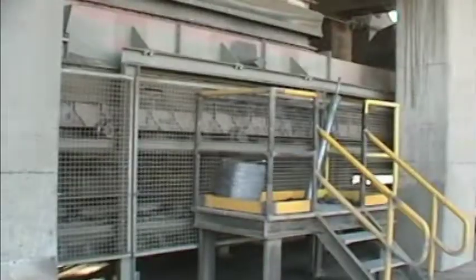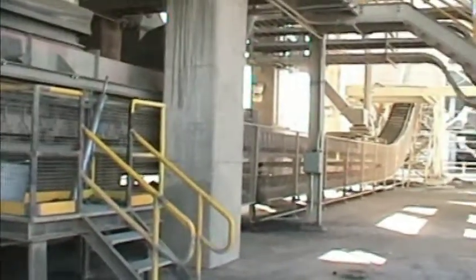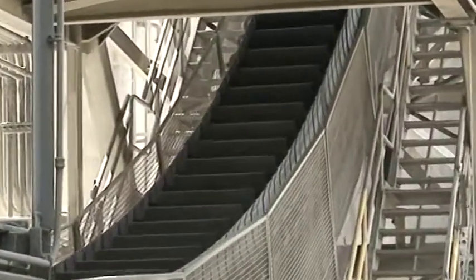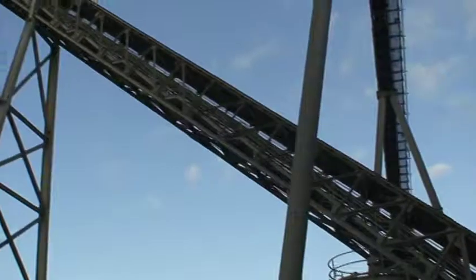Once in the cooler, 8 fans underneath introduce ambient air, quenching the clinker in 20 minutes to a temperature as low as 125 degrees. 4 hydraulic roll breakers at the back of the cooler break up the clinker to a size of 1 inch or less. A pan conveyor located underneath these breakers sends the material up to one of 2 30,000-ton clinker silos.